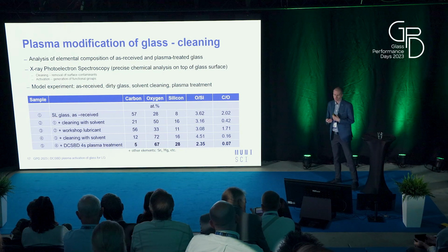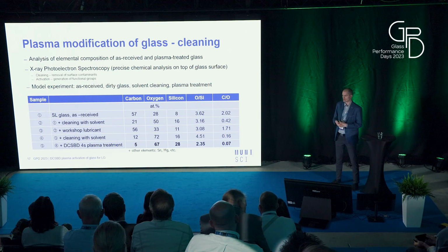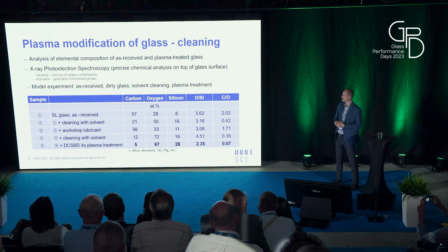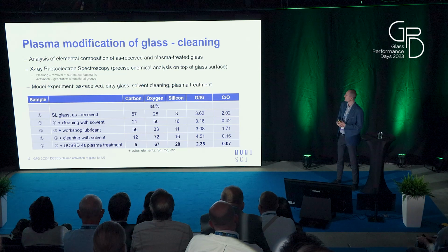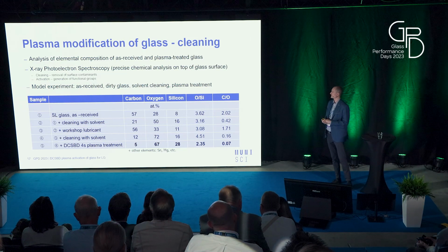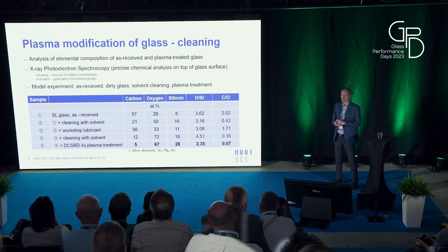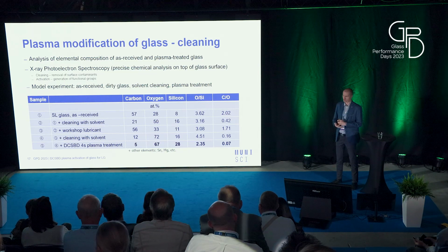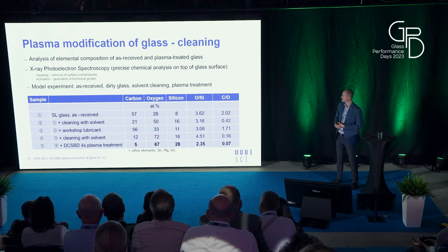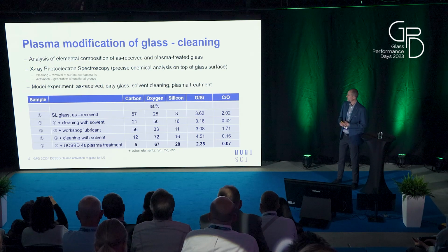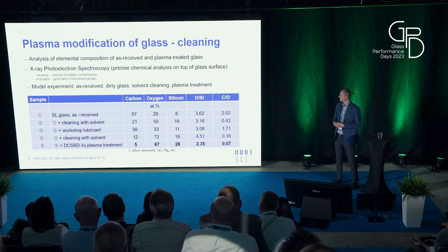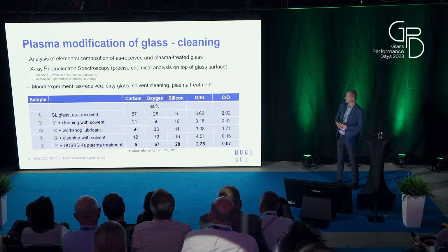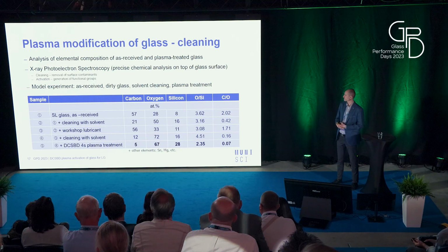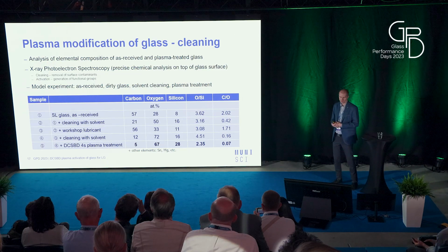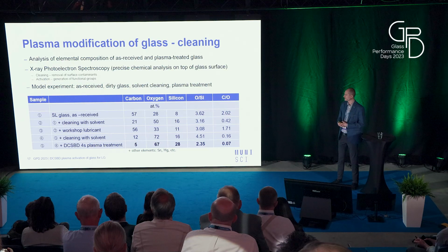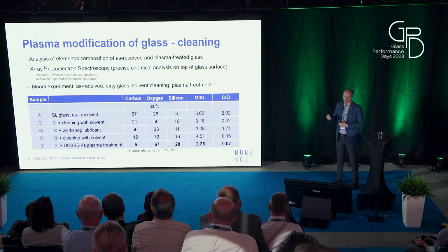What is important is that plasma can clean the surface. It means that we can remove some organic or inorganic particles or any contaminants on the surface. For analysis, we used X-ray photoelectron spectroscopy. This is a method which can be utilized to measure very precisely the concentration of elements on the surface of plasma-treated glass. Here we can see that for the as-received glass the carbon concentration is around 57 atomic percent, and if we compare it with the standard wet cleaned glass, the concentration is around 21%. But on the other hand, when we apply plasma for a very short treatment time, the carbon concentration decreased to only 5%.